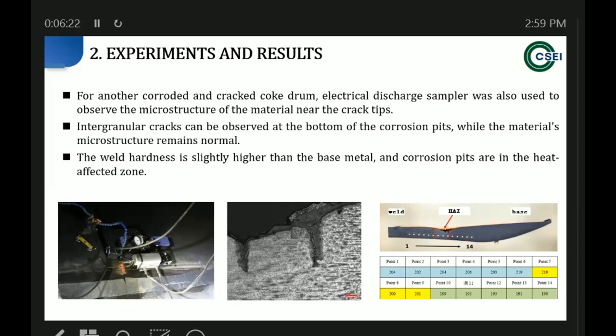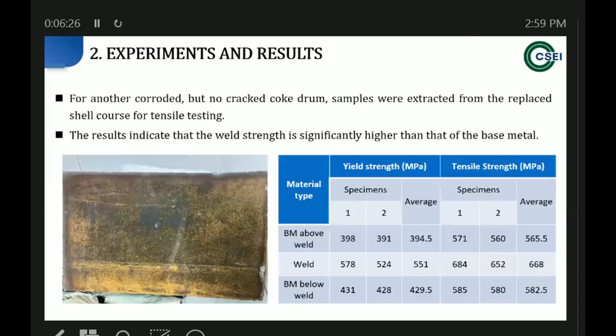We can see the weld hardness is slightly higher than the base metal. And this is case three. We take a sample from the replaced shell, and we test the tensile strength for this material. And this is a corroded coke drum, but no crack was found. So the results indicate that the weld strength is significantly higher than that of the base metal.